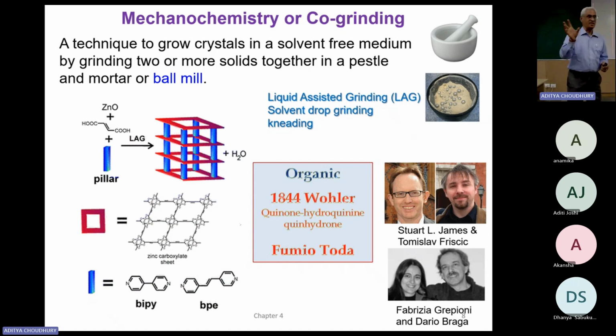That's how it's hopping. A drop of solvent is hopping, that is what is happening. The same thing when you grind without anything, that's neat. That's what they say. Without any solvent, the heat is produced, sometimes it melts, the reaction occurs. So you get the product, no doubt about it. After that, you just leave it, right? Those where you have drops of solvent present will be used to crystallize. But not every crystal, not all the powder will be converted into single crystal. You see a few single crystals based on how much solvent you added.